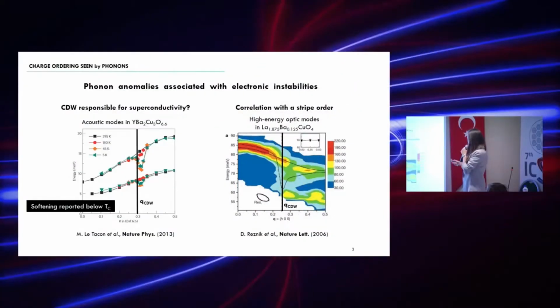Charge density wave order can also affect the lattice dynamics of the material, and it was shown in 2013 that around the Q vector of charge density wave order, an anomalous softening of acoustic phonon modes appears. It was shown for yttrium barium copper oxide. And this softening, as was said in Catherine's presentation, is reported below TC and also within the doping range where superconductivity occurs.